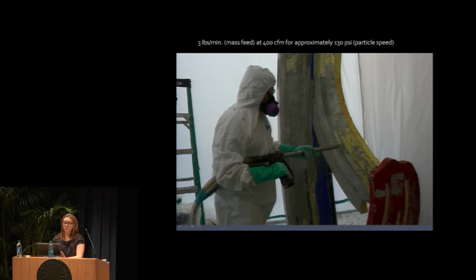I think they ended up using quite high pressure. At the time, it was hard for me to gauge what's the limit. They were using up to about 130 PSI. They switched the nozzles to try and optimize the paint removing. And I did have some concerns about applying pressure on the surface of aluminum. It's about a 1/4-inch thick sheet that's been fabricated and welded. So there was concern about the structure and the surface.